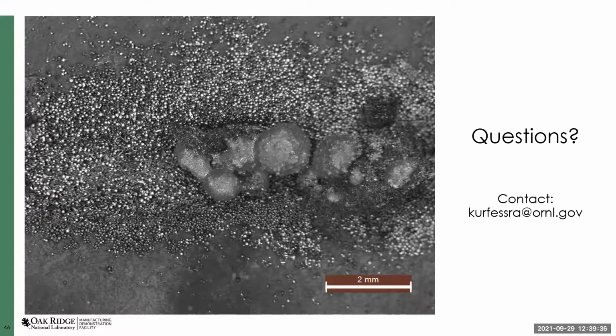And I think the other thing is support removal. One of the nice things about polymers is that, first of all, what we found with the research is that the metal is very, very easy to remove. When I print these parts, if I accidentally tilt the substrate too much, the metal will just fall off. So ease of removal is a big deal. And even if we did have to machine away the polymer, machining polymer is significantly easier, takes less energy, and you are less likely to ruin or break your machine than when machining away metals. So I think those are my two big considerations with the low temperature metals. Great.